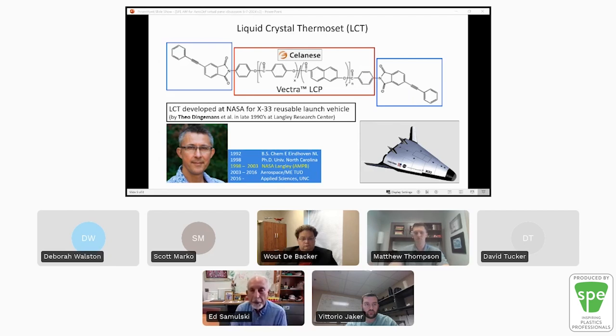And he did this by making an oligomer based on a liquid crystal polymer called Vectra that was made by Celanese. Instead of making a high molecular weight polymer, he made a low molecular weight oligomer and put reactive end groups on that oligomer. When you put that together and make a composite with carbon fiber, it's fantastic, in part because the coefficient of thermal expansion of the liquid crystal polymer is essentially identical with that of carbon fiber. So you can cycle it in temperature without any degradation. And so we started to think, well, maybe this could be a generic way of making intractable, hard to process polymers more tractable: make oligomers from them.